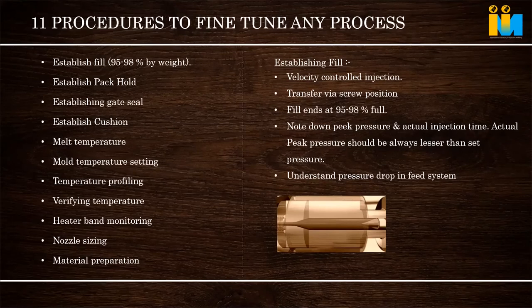Based on that, I will come to know what amount of pressure drop is happening when it is crossing the gate, the runner and the screw. If more pressure drop is happening in the gate, we have to attend to the gate. If it is happening in the screw, we have to attend to the screw. If it is in the runner, we have to attend to the runner. If the gate is showing only 10 MPa and the screw is showing 20 MPa, we have to attend to the screw. Attending to the gate will not help us.